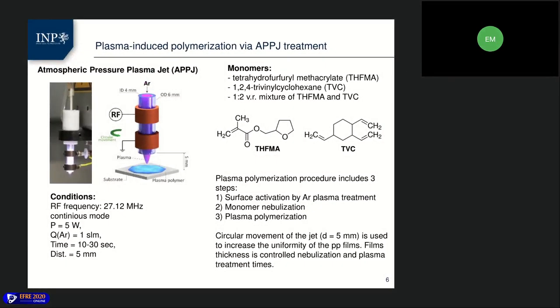Thanks to the reactivity of carboxyl groups, carboxyl-rich plasma polymers are extensively employed for numerous biomedical and environmental applications, including immobilization of biomolecules. In this study, an atmospheric pressure plasma jet was employed for deposition of thin polymeric surfaces for their use in biosensing. The radio frequency atmospheric pressure plasma jet was operating at 5 watts in continuous mode with one SLM of argon. Monomers for the plasma polymer film deposition were tetrahydrofurfuryl methacrylate and trivinyl cyclohexane, and a mixture thereof with the volume ratio of 1:2. The distance between the jet outlet and the substrate was kept at 5 mm.